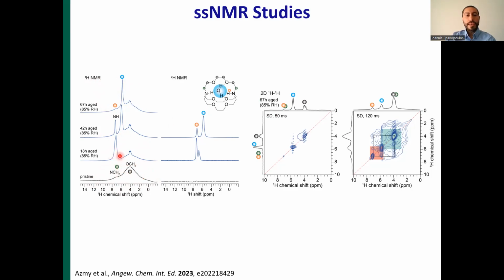But with aging and exposure of the material at 85% relative humidity, we observed that gradually these signals were resolved, and also, at much higher times, the peak of water was also recorded. So this was not that conclusive.